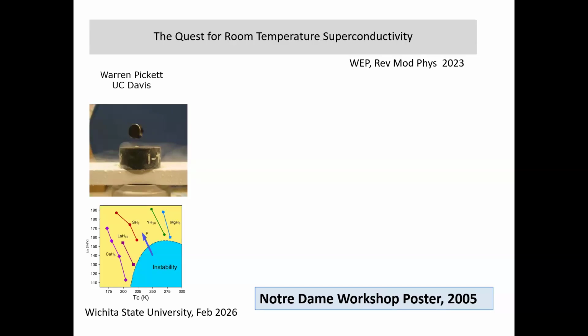And he measured a little bit lower and was getting 0, 0, 0. And he quite properly stated that actually he couldn't prove it was 0, but the upper limit of the resistance was really quite small, like a 10,000th of what it was before, something like that. So that's the primary feature of a superconductor. There's a normal metal up here, and it's a superconductor down here with no resistance, which is fascinating and potentially important. My early slide will show this. And there's a magnetic effect also, which I will talk about.